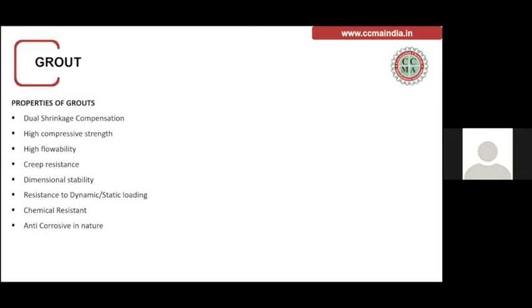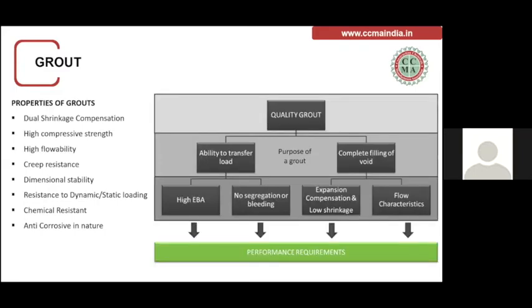Chemical resistance, of course, is one of the important parameters, so that the grout does not get damaged at a later stage because of chemical ingress in the structure, which we usually see in many project sites. And anti-corrosive in nature is another very important aspect, because the reinforcements embedded inside these grouts should not get corroded. So these are some of the properties of the grout material.